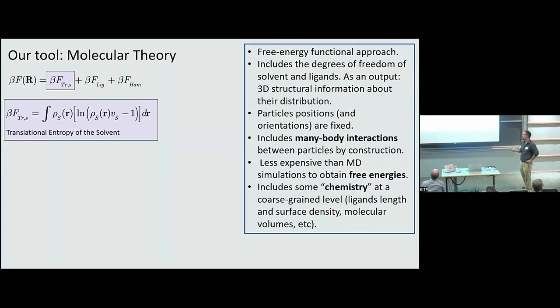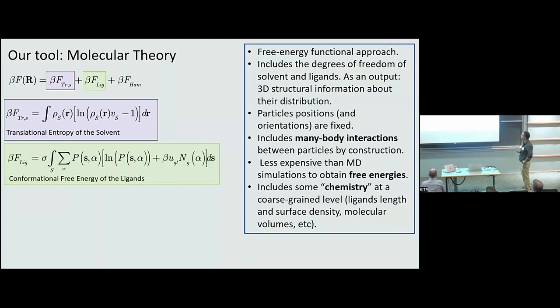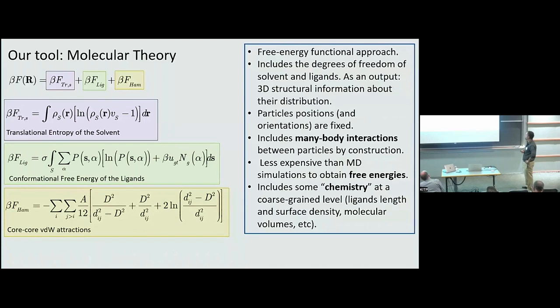Then this other term is the conformational entropy of the ligands. Here there is an unknown function that is p alpha, that is the probability of having a certain ligand in a certain conformation that is given by alpha. So what we do is we generate a lot of different conformations for the ligands using some Monte Carlo algorithm, and we fit the theory with that. And the theory decides what is the probability of each of those conformations on the surface of the nanoparticle. And then we have a term that's related to the core-core van der Waals interactions.